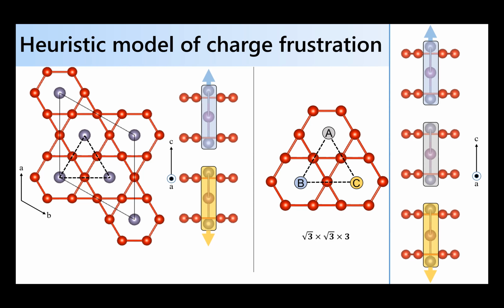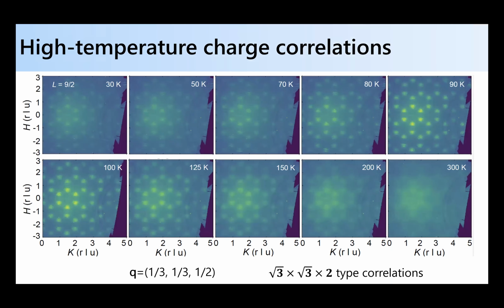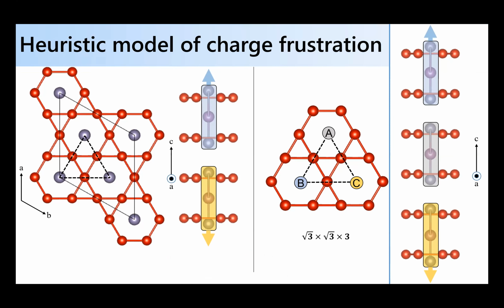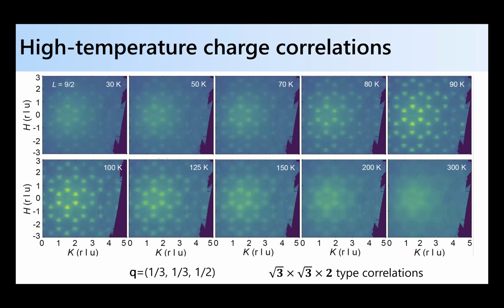So what's the relevance of this at all, right? So the answer is that if you look with X-ray scattering, the charge order transition of this compound is at 90 Kelvin. But if I look at a wave vector that corresponds to this periodicity, so a third, a half, okay, what I'll call this frustrated type of order, there are extensive charge correlations that are present even at room temperature, okay? And so what happens is as you cool down, these charge correlations get more and more intense. You have a three-dimensional first-order transition to three-dimensional long-range charge order, but these charge correlations still stick around and dampen as you cool through. So these residual correlations are the primary energy scale in the system. They're present at high temperature. They're just frustrated from driving long-range order until you can unlock this additional degree of freedom along the chain.